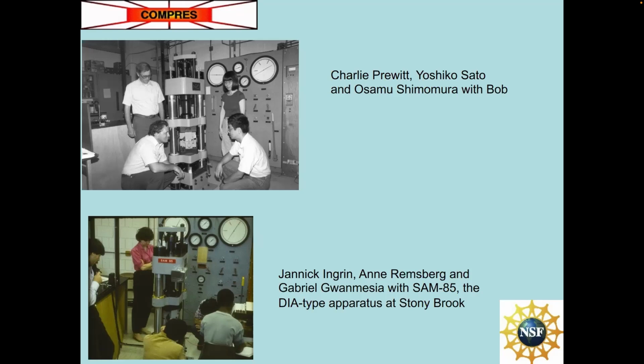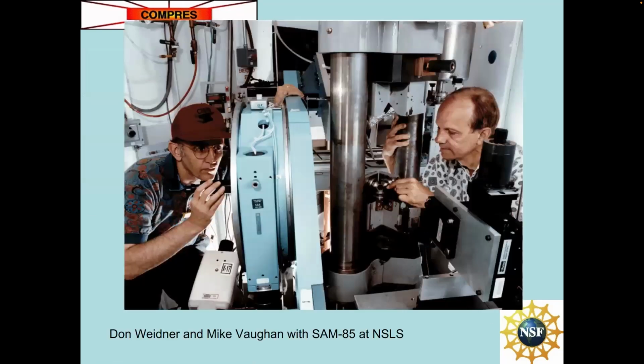And it has the distinct capability, compared to the other kinds of multi-anvil apparatus that we've used for synthesis, that it has easy access to synchrotron radiation. And the next slide should show Don Weidner and his colleague Mike Vaughan installing this apparatus, SAM 85, at the National Synchrotron Light Source at Brookhaven. You can see the anvil system consists of 6 anvils, 3 of which are shown next to Mike's finger, and they compress a cubic cell assembly into which you can introduce X-rays and acoustic signals and directly measure both the sound velocities of the materials, but also the structure, and just as importantly, the length of the specimen.